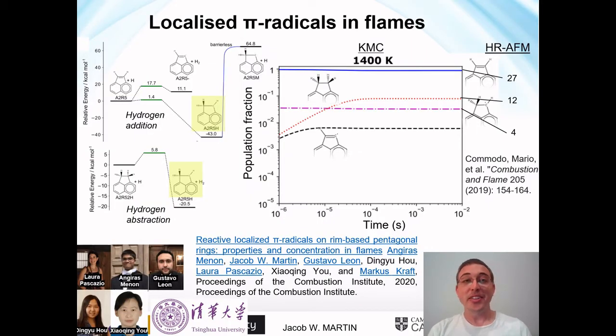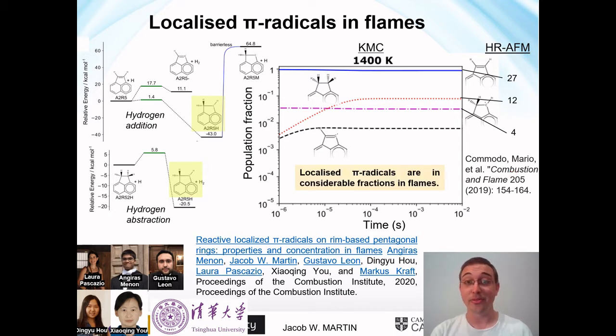But I guess another question is whether these localized pi radicals are even present in the flame. So we teamed up with a group at Tsinghua University to create a kinetic mechanism that was able to explore hydrogen adding and removing from the edges. So we could actually predict how many localized pi radicals would be expected in the flame at a variety of temperatures. And we found that it is a dominant radical, so this purple line here shows it is in higher concentration in some instances than sigma radicals, where a hydrogen is removed from the edge. And it also aligns with what we see in the atomic force microscopy. So they are in a considerable fraction in flames.